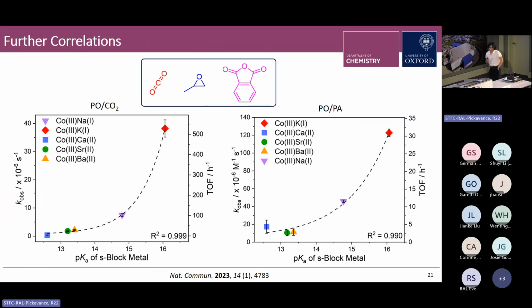I should mention this is not the first time that we've seen these kinds of exponential activity-acidity correlations. We've also seen it for the same series of catalysts when tested for a different epoxide, so propene oxide instead of cyclohexene oxide, in the case of the copolymerization of PO and CO2. And in the case for PO and PA, we also see exponential increases in catalytic activity with decreasing S-block metal Lewis acidity.